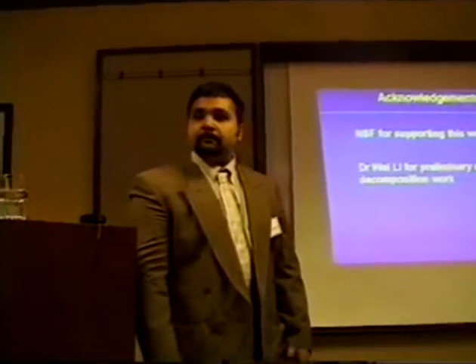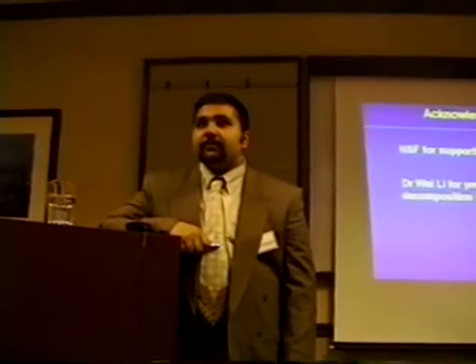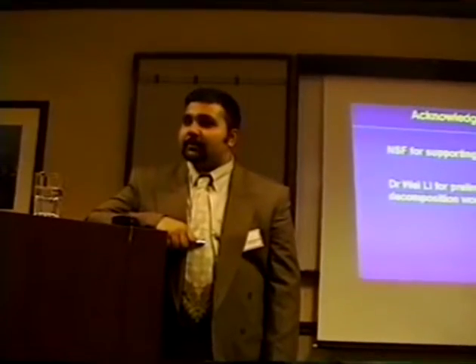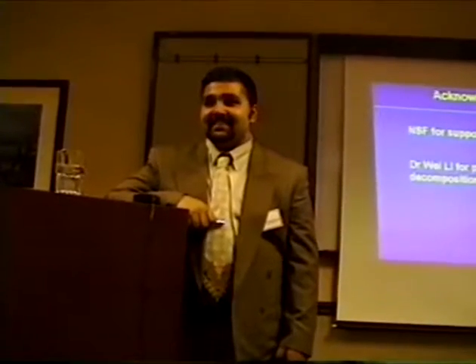Your activation energy seems to be too low for a chemical reaction. Have you ever wondered about that? Well, the activation energy for adsorption is... Adsorption, you presented 5 kJ per mole, which is 2 kcal per mole. Yes. Which seems to indicate maybe it's a physical adsorption going on, or maybe there is some coverage effect in your kinetic data. Have you ever wondered?